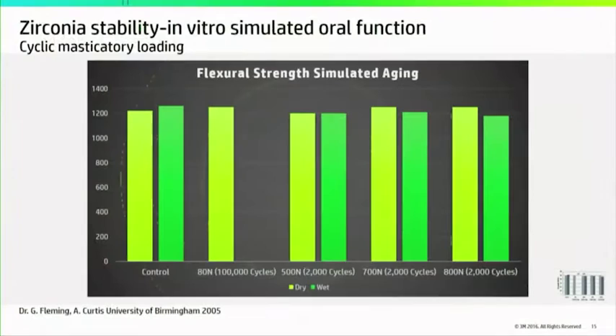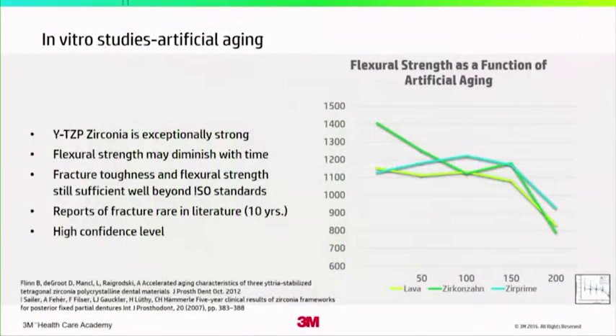Now, when it comes specifically to zirconia, there are a number of studies that show us how zirconia behaves in the mouth. And, of course, in vitro testing is certainly not the same thing as in vivo evidence that we're all familiar with, but this is what an evidence basis is really all about. What we see, particularly with Lava zirconia, is that these specimens, when subjected to cyclic masticatory forces in a wet and dry environment, show no significant decrease in strength for the Lava frame zirconia. And in fact, this is what I've seen clinically in my own practice over the years. At the same time, even with the scattering in the data we see here, the reliability factor for this particular material, produced by this manufacturer, has not changed whatsoever, and we can be confident that we have reliability.